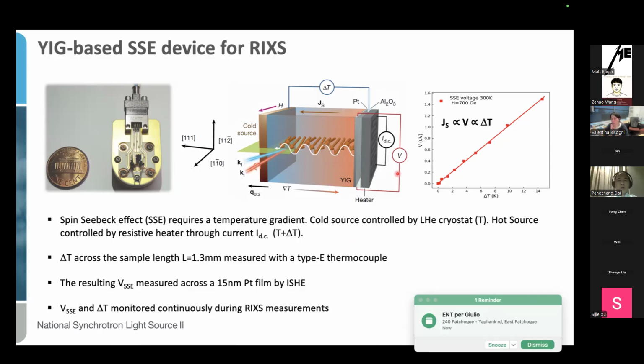I see. So you also checked that when there's no temperature gradient, your plus minus Q intensity completely obeys the Bose population factor, right? As you would expect, right? I mean, the plus minus Q pure magnon excitation in equilibrium is modulated mostly by a tiny bit by the RIXS cross-section because we need to change the geometrical condition a little bit. And there is a small change. I see. No, actually, I asked the wrong question. I guess the energy gain and energy loss at the same Q, does that actually follow the detailed balance factor, right? Okay. Yes. Okay. Thank you very much.